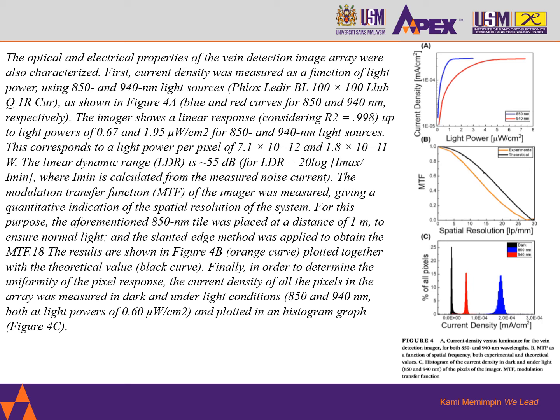The optical and electrical properties of the vein detection imager array were also characterized. First, current density was measured as a function of light power using 850 and 940 nanometer light sources, as shown in figure 4a. Blue and red curves are for 850 and 940 nanometer respectively. The imager shows a linear response, considering R2 equal to 0.998, up to light powers of 0.67 and 1.95 microwatt per centimeter square for 850 and 940 nanometer light sources. This corresponds to a light power per pixel of 7.1 x 10^-12 and 1.8 x 10^-11 watt.